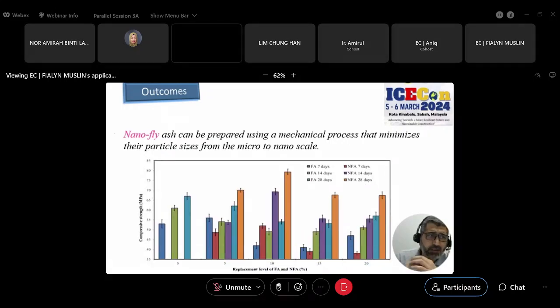So nano fly ash can be prepared using a mechanical process that minimizes their particle sizes from micro to nano scale. In this bar chart, you see the effect of different replacement ratios, or levels, of fly ash and nano fly ash on the compressive strength. And you can see from here that the use of 10% was the most optimum percentage in improving the compressive strength of concrete, up to, I would say, from 60 to 85 megapascal, which is huge. But then they noticed that it can start decreasing. So the results showed that the 10% of nano fly ash or fly ash is more optimum to improve the compressive strength.